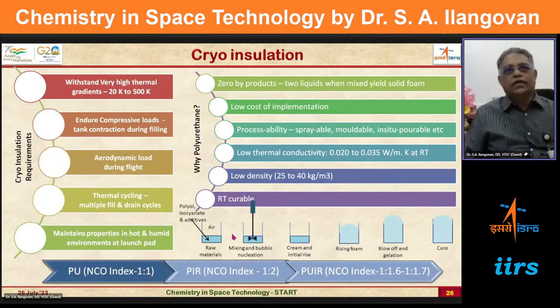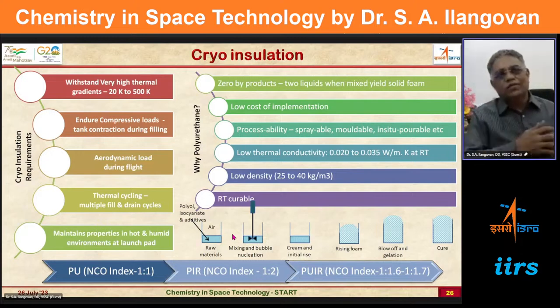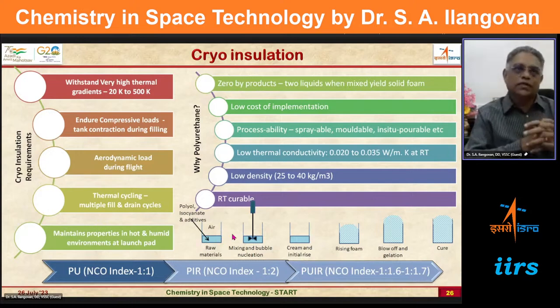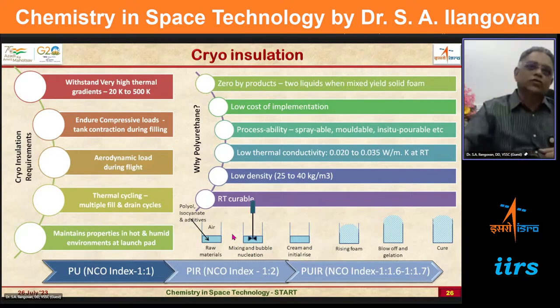One is that it has to withstand the high thermal gradients of 20 Kelvin, and outside when the launch vehicle is moving at a high speed of about 2 to 3 kilometers per second, a lot of heat will be generated on the surface because of the dynamic pressure as well as the atmospheric gaseous molecules. So polyurethane has to see a window of nearly 500 Kelvin it has to meet. Then compressive load has to be met, then aerodynamic load during the flight, and thermal cycling, because if there is a launch call off, we'll have to drain the liquid hydrogen and again refill it, so that causes thermal cycling.